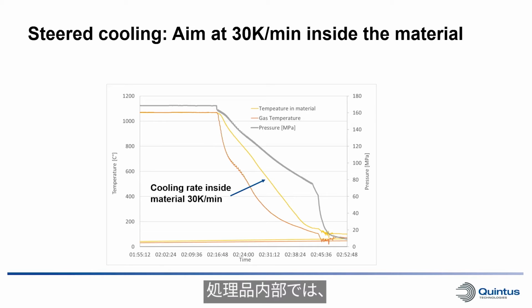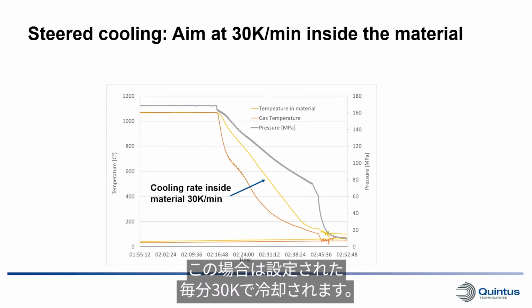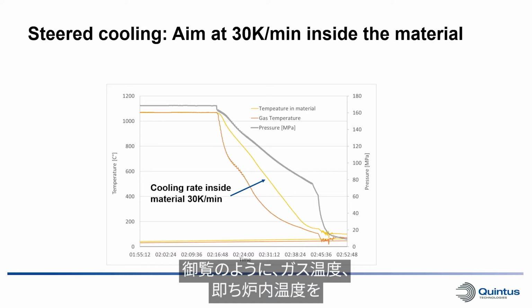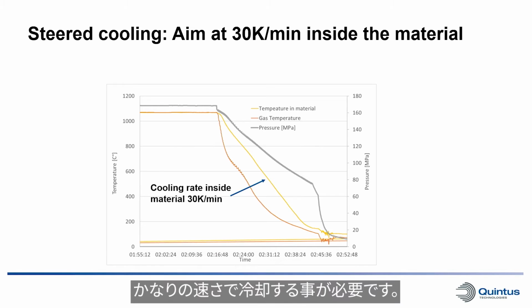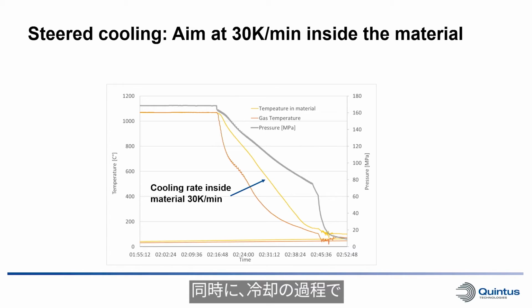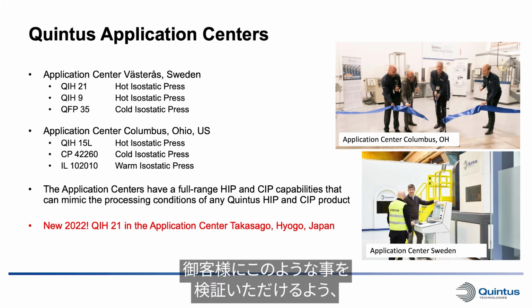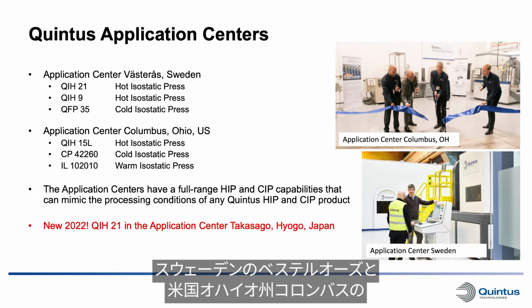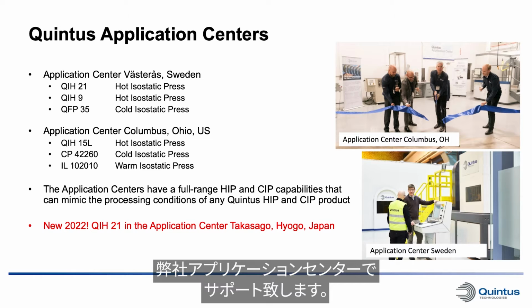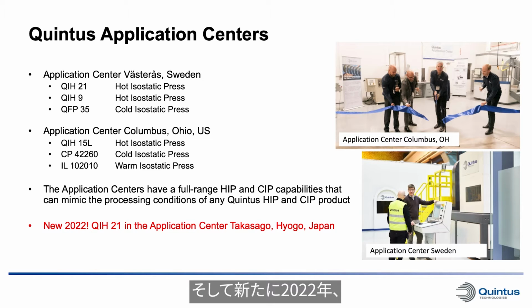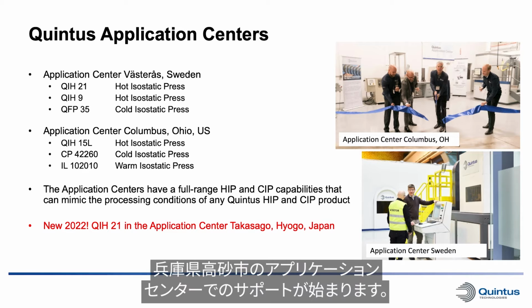The cooling curve from doing a run like this, you can see in this graph. We will have a cooling rate inside the component equal to the set cooling rate, in this case 30 K per minute. You can see that the gas temperature, which is the furnace temperature, needs to be cooled off significantly faster. And at the same time as the temperature drops during the cooling, also the pressure will drop. So this kind of investigations we can support you with in our application centers in Västerås, Sweden, and in Columbus, Ohio, USA. And new for 2022, we are setting up these possibilities also in the application center in Takasago, Hyogo, Japan.